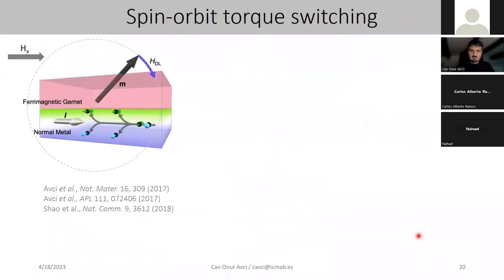Okay, so now we know that we can detect the magnetization. So what about spin orbit torque switching? We know that spin orbit torque works well in the metallic case, so now we just apply this to an insulating case. We have a garnet and a normal metal, and we send a charge current that generates a spin current in the transverse direction because of the spin Hall effect. That spin current generates a damping-like torque on the magnetization, and that can switch the magnetization between up and down states.